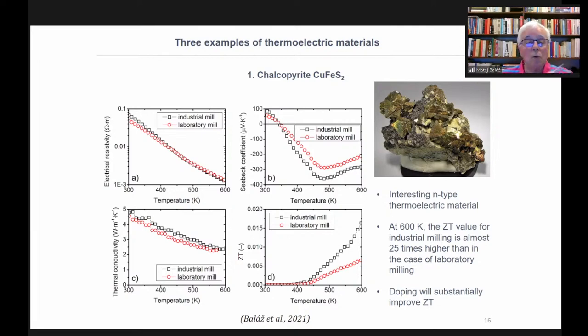And if you look at these plots, which are needed for a figure of merit calculation, electrical resistivity, Seebeck coefficient, thermal conductivity, finally, you can see these ZT values. And in principle, ZT values for the industrial mill are higher in comparison with the laboratory mill. Of course, there is a lot of work on how to improve the figure of merit. It is done by so-called doping, etc. But I wanted to show you the principle of this.